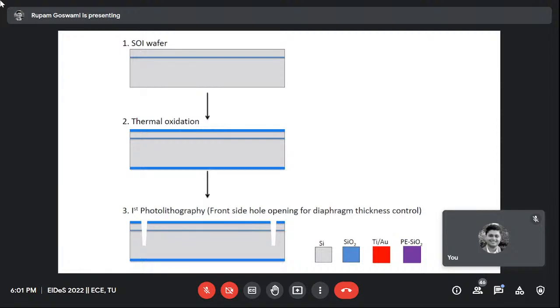So in SOI, as I mentioned earlier, when you take the SOI route of making the sensor, then you have to have the silicon 100 substrate, of course, and this is the ready-made wafer. The oxide layer is also there in it, and the top layer is the active layer. And this active layer is a layer of crystalline silicon, of course, of required resistivity and thickness, so that when we make the resistor from this layer, the required resistance of that resistor will be obtained.